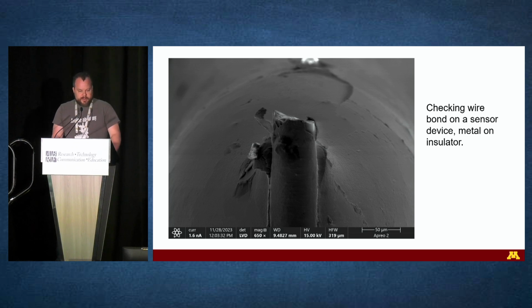Working with another local company, these are oxygen sensors from ventilators that they started making rapidly during the pandemic, and they were having trouble with some of their sensors failing. So this is actually checking the wire bond for the sensing wire at the top of the ceramic and polymer posts, and we can see that there's an awful lot of material peeling off around the edge. So there's a good reason for why this sensor is failing. There's no conductive path for the sensor there.